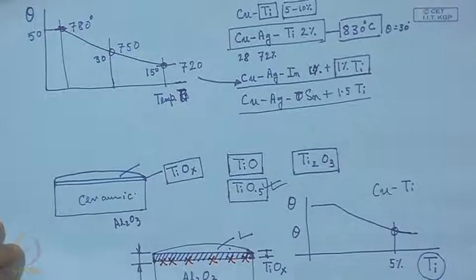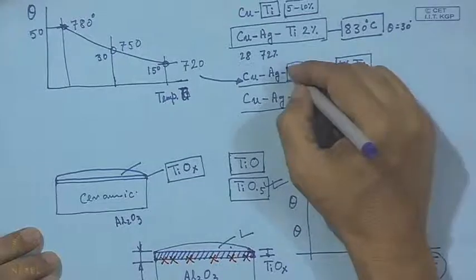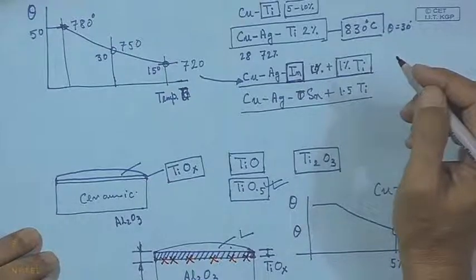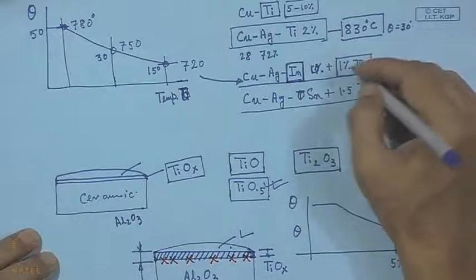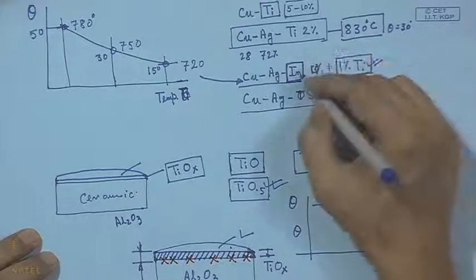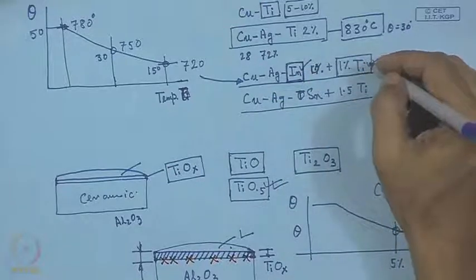And to achieve that, one has to formulate this alloy in such a manner that the role of the ternary element is well realized, well understood, and it plays one of the important roles to always promote the activity of this reactive element. That means its role is basically to reduce the solubility of this reactive material in the basic parent material.